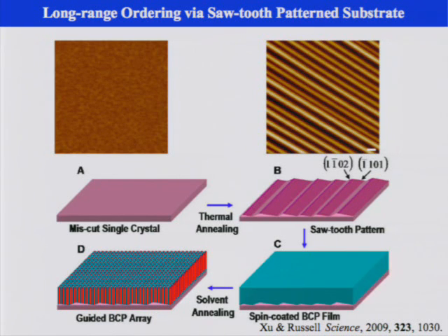If you miscut a crystal at a certain angle and then re-anneal it, the crystal is going to generate a sawtooth pattern, and this angle is dictated by the crystal plane of this inorganic material. In the microscopic distance, you should see the ridges or sawtooth pattern go in one direction, and that direction is dictated by the crystal growth. If you can get a very large crystal, you can easily get the trenches ordered toward one direction.